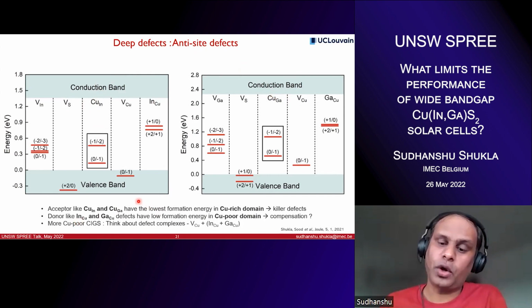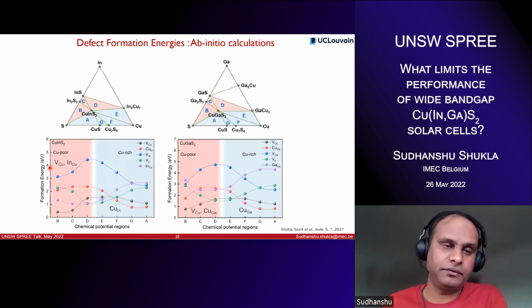However, when you move to the copper-poor domain, you have the lowest formation energies of the copper vacancy, of course, which is an acceptor dopant in your material, indium over copper and gallium over copper.